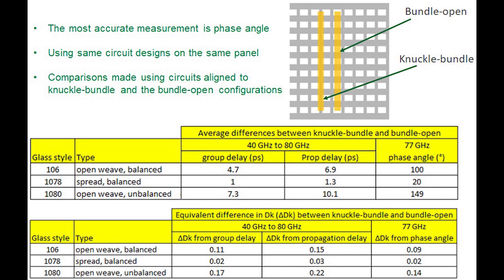Shown here is some information from the study that we did a few months ago on the Glassweave pattern, and really what we were looking at was the local trace environment, because that is something that we could capture very accurately. And it was a very time-consuming and tedious work, because basically what we did is on one panel we made a lot of circuits, about 80 circuits, and we inspected every one of them looking for the exact alignment